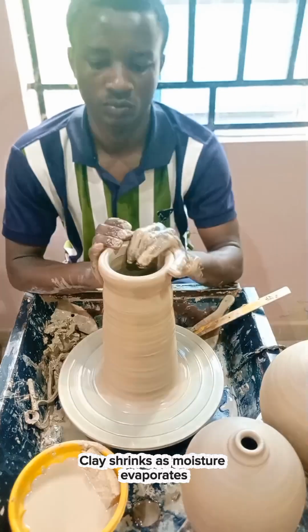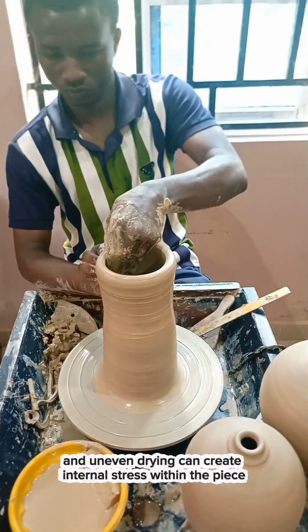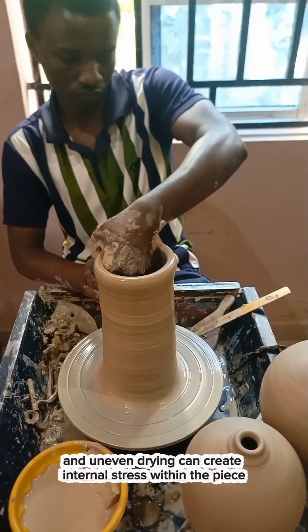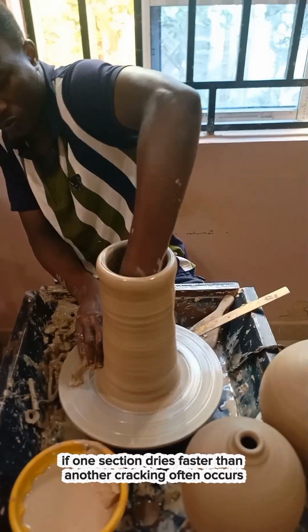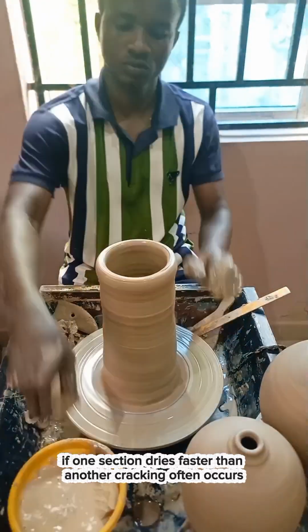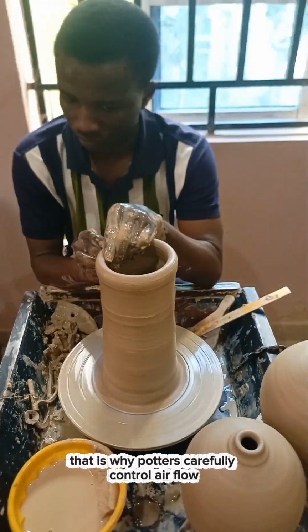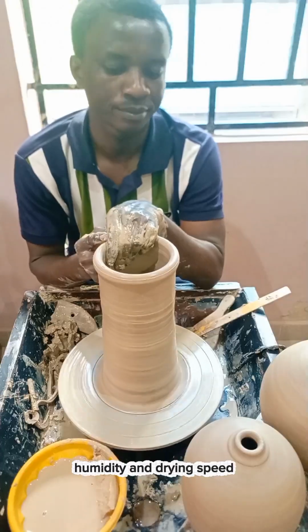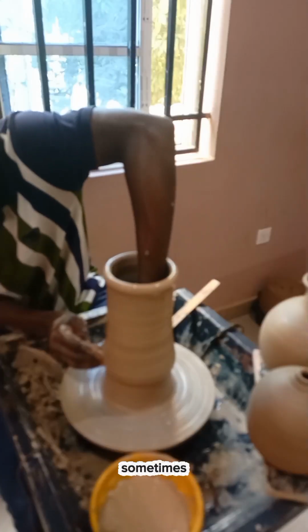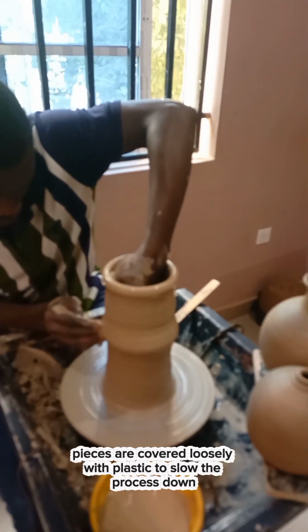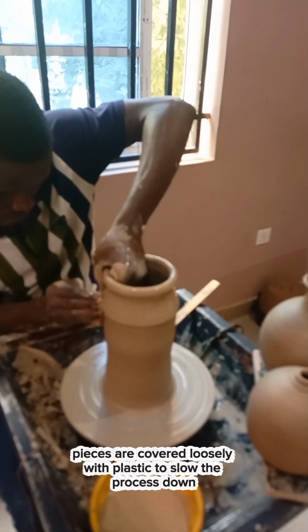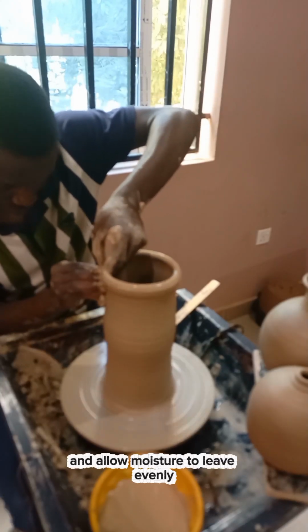Clay shrinks as moisture evaporates, and uneven drying can create internal stress within the piece. If one section dries faster than another, cracking often occurs. That is why potters carefully control airflow, humidity, and drying speed. Sometimes pieces are covered loosely with plastic to slow the process down and allow moisture to leave evenly.